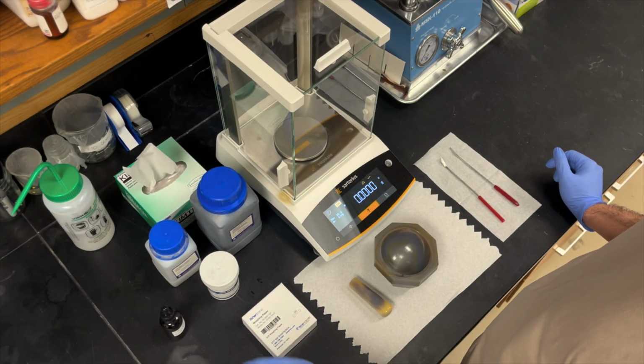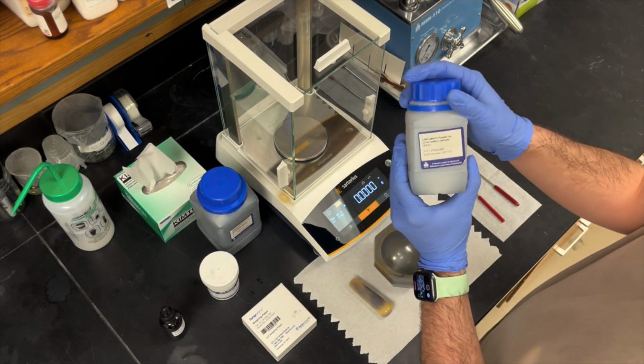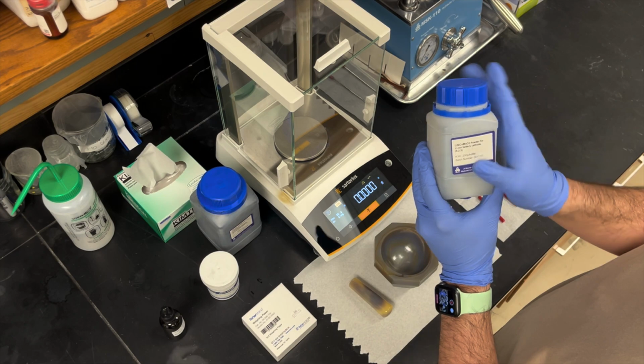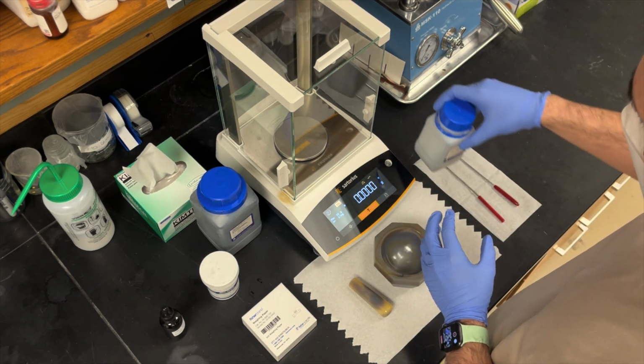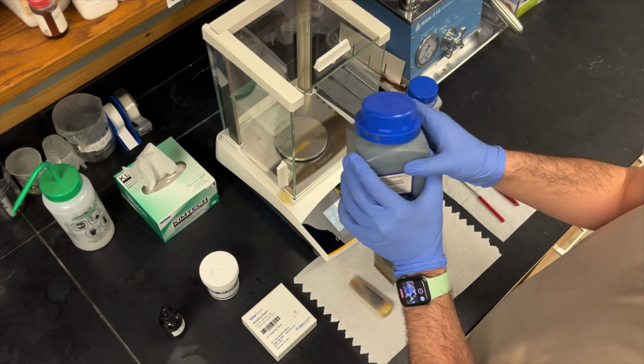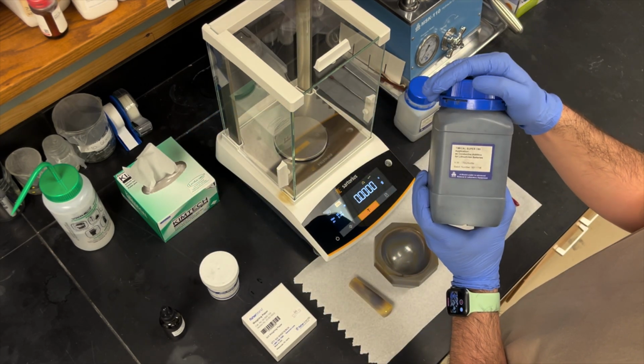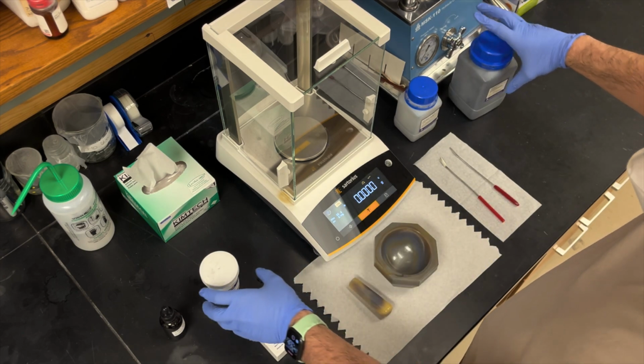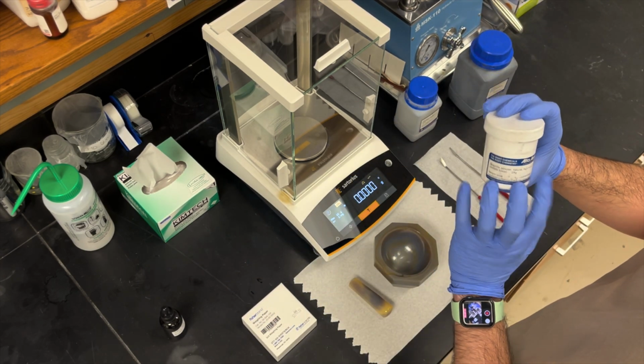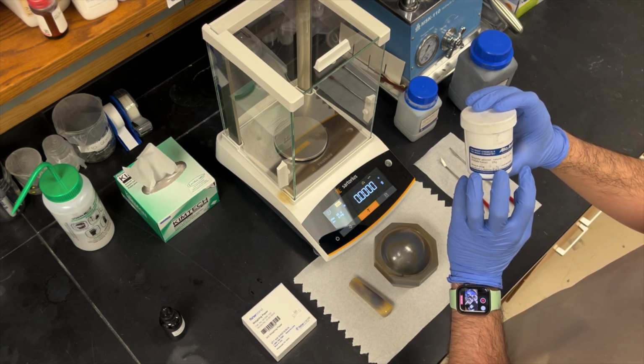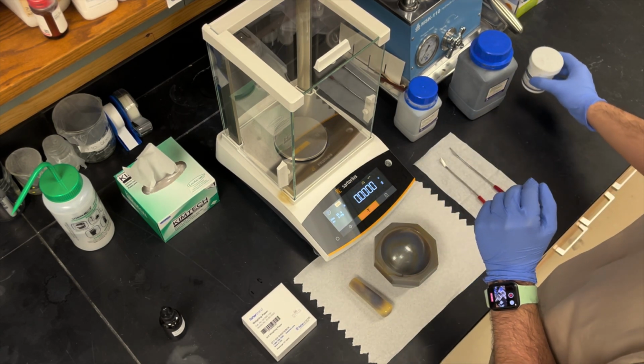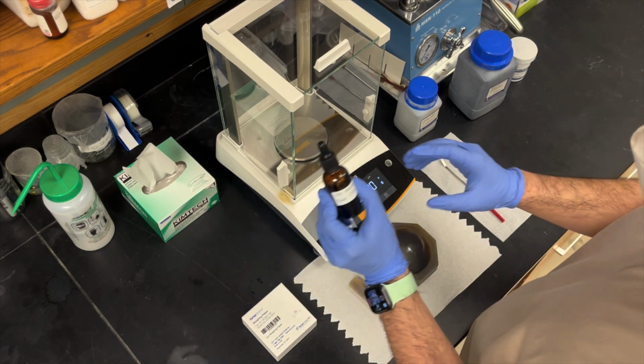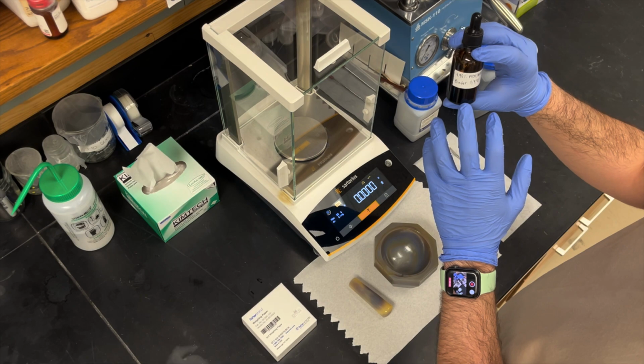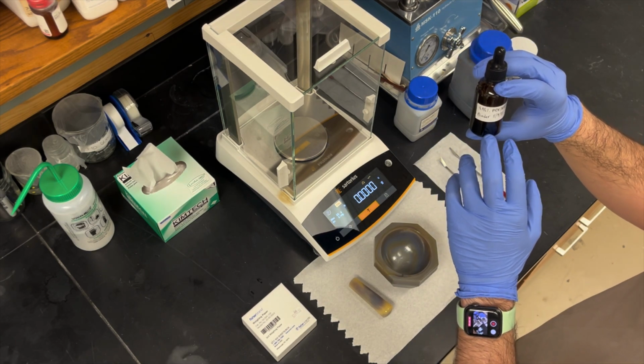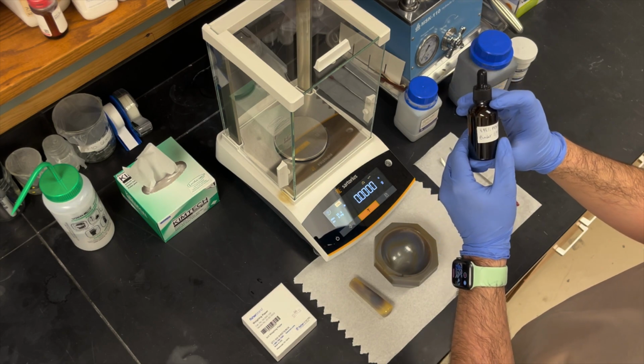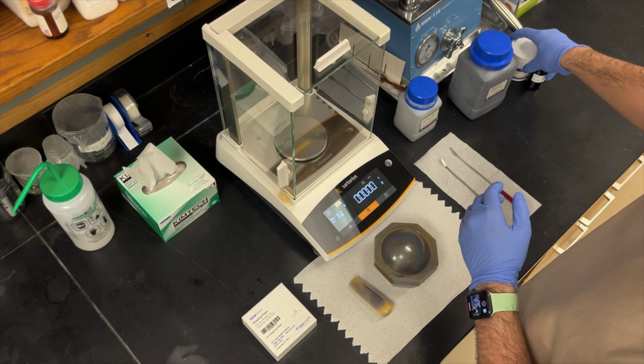Here I will show off the ingredients for the slurry, where we have a lithium compound containing nickel, cobalt, and manganese, or NCM, which is used for the cathode. We also have carbon black, which is another component of the slurry. And then we also have graphite powder for the anode. We then also have a binder solution containing polyvinylidene fluoride powder, or PVDF, dissolved in 1-methyl-2-pyrrolidinone, or NMP.